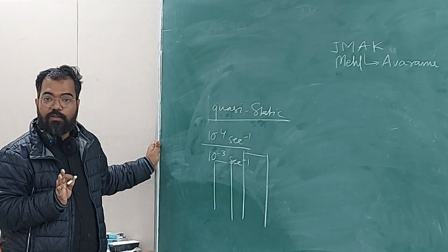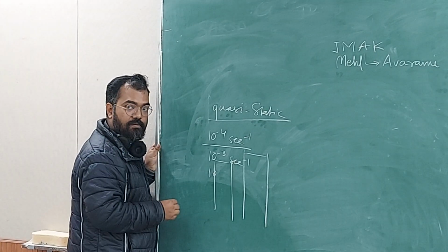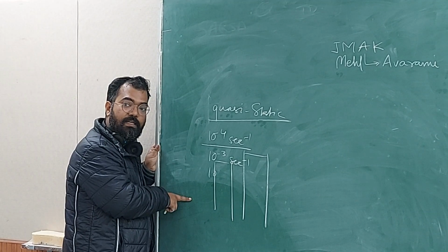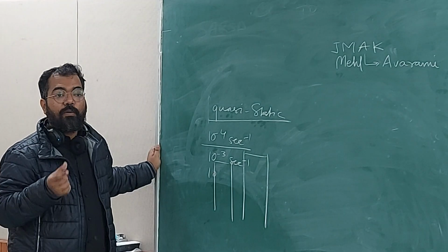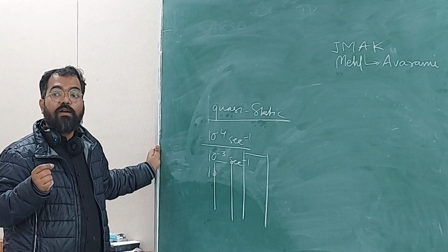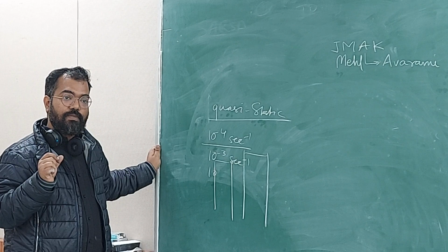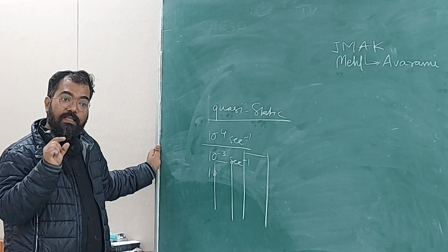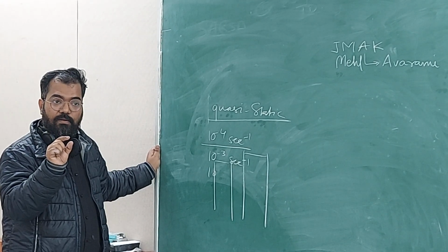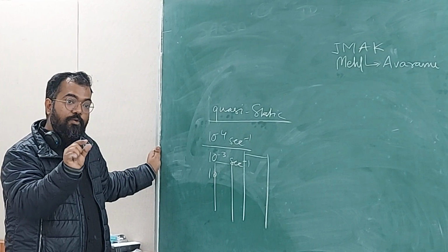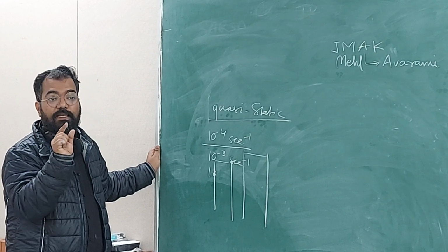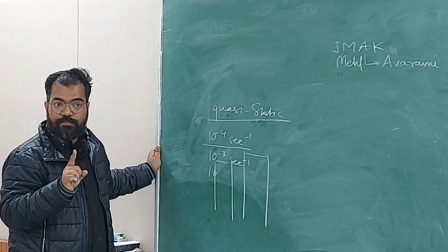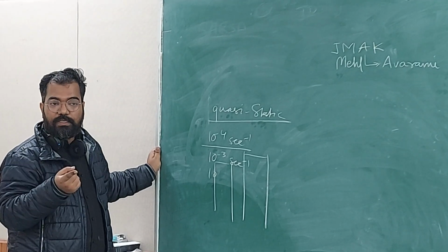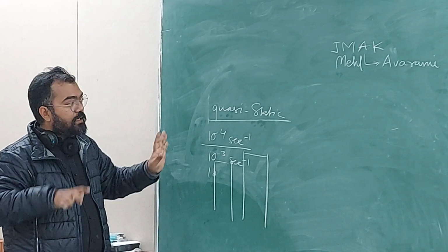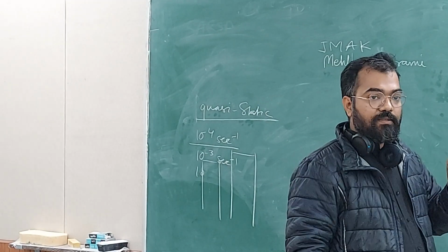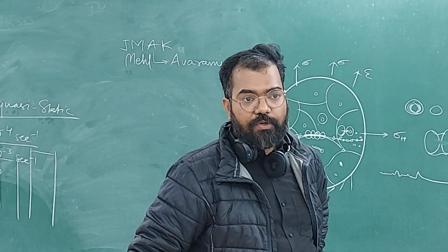10 to the power minus 2 also you might not see. But if you go to 10, then you will see. In order to see any significant difference in the material deformation, meaning any time dependent phenomena is shown by metallic materials, you need a very great change in strain rate. Okay, so when you do a Charpy test and then you touch the sample, it will be hot. But if you do a tensile test and you touch it and it is hot, that means you are doing it either at a very high strain rate or there is some transformation going on. There can be a phase transformation going on while you are doing the test. That can give heat. Because mechanically you should not get any heat when you are doing any slow testing on metallic materials, and metallic materials usually whatever we do are slow.